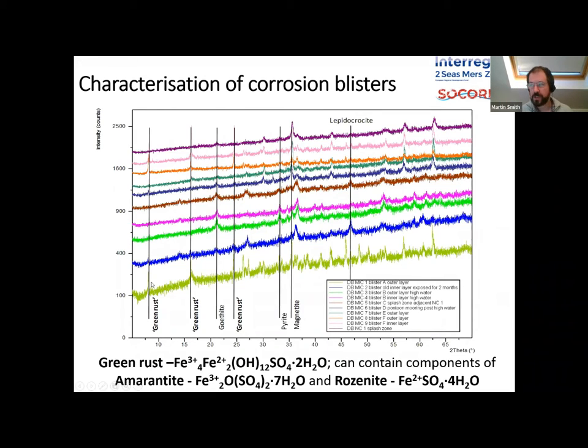So the first thing is when we look at X-ray diffraction patterns, so this is 2 theta against intensity, iron-rich samples, unfortunately, with copper K-alpha, so we get high backgrounds. But we can see lepidocrocite, we can see magnetite, we can see pyrite. And throughout all of this microbially influenced corrosion-type material, we get green rusts. So if you're not used to green rust, it is actually something that has a formally recognized mineral formula and structure. So it's called green rust, but it is a recognized phase. And what it is is iron 2, iron 3 hydroxide sulfate hydrated. And that includes components of amarantite, so iron 3 oxysulfate, and rozenite, iron 2 oxysulfate.